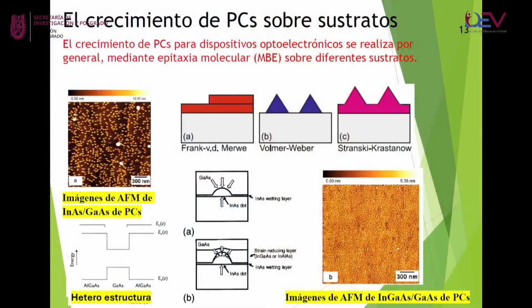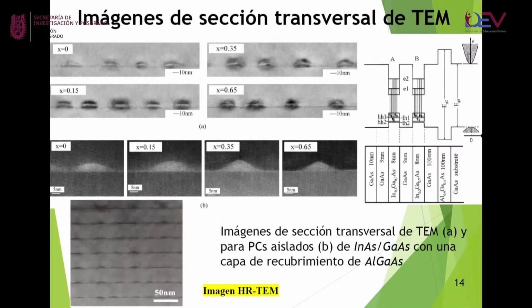After that, you could see here quantum dots without covering, but before putting the quantum dots outside the chamber, quantum dots are covered by a confining barrier. At first, you could see here images of transmission electron microscopy, and you could see the buffer layer, quantum dots, and capping layer. It's possible to have one line of quantum dots, or multiple lines of quantum dots separated by barrier. Here you could see a multi-structure, like a sandwich structure, with quantum dots separated by gallium arsenide barrier.